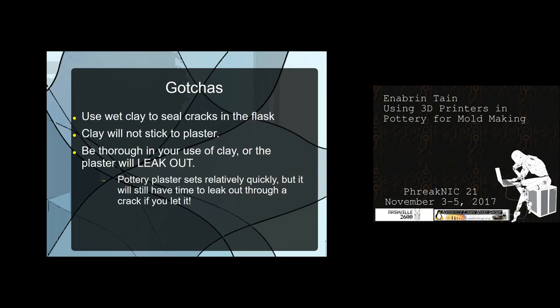Clay does not stick to plaster — that sounds counterintuitive because you're using plaster to make something out of clay. The way the plaster works is it's pulling the water out. When clay gets its water pulled out, it tends to shrink up and separate. That works for us when we're doing mold making, and it's also the mechanism we use for the actual slip casting.